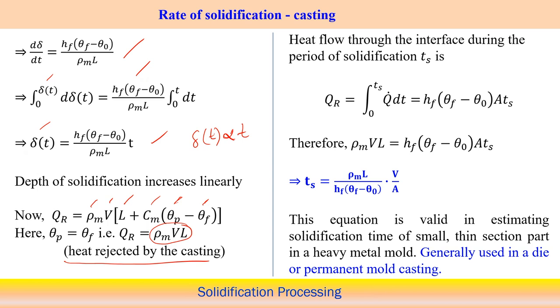Now, consider the heat flow through the interface during the solidification time T s. Over the solidification time, what is the total amount of heat release? This is the heat rejected by the casting over the solidification time T s, and it depends on the volume of the casting. If you know the total volume of the casting, and it is only changing phase from liquid to solid, then rho m v into L indicates the total amount of heat release over the period of solidification.